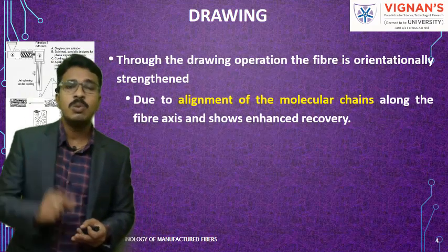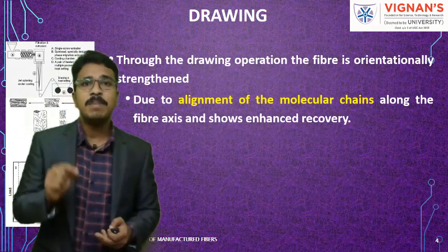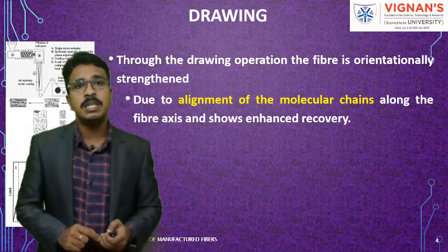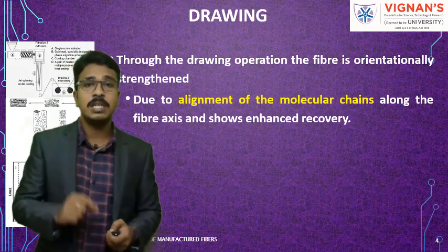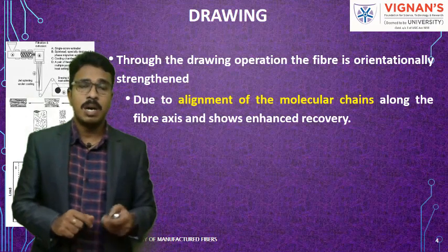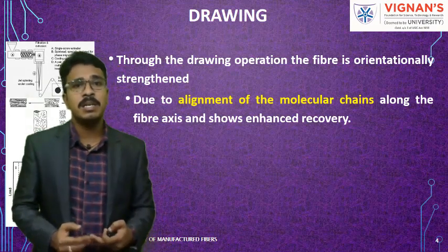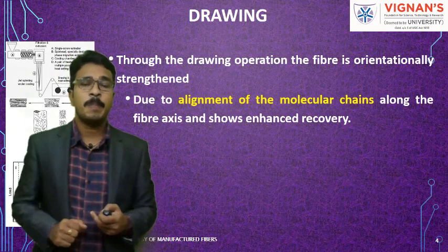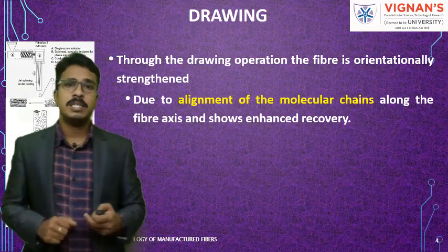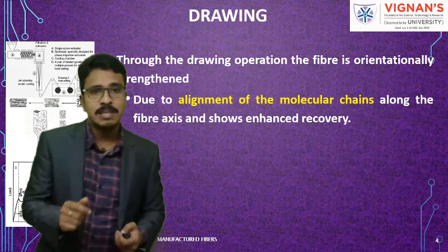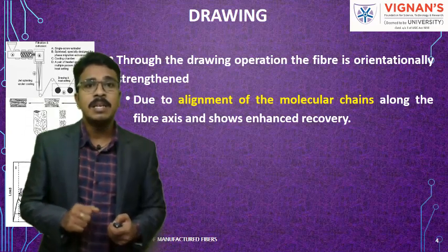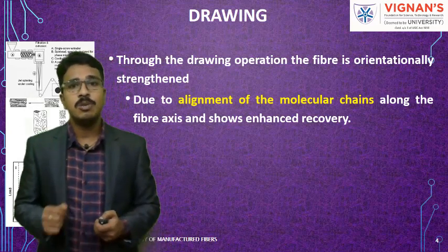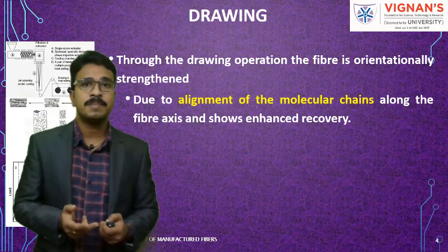Through the drawing operation, the fiber is orientationally strengthened. This orientation comes from the alignment of molecular chains along the fiber axis, and it shows enhanced recovery.